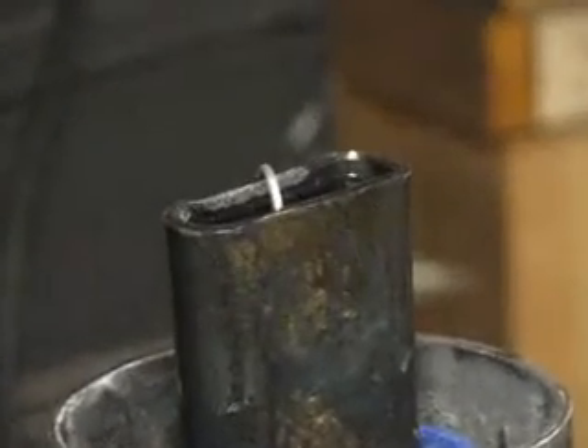Immediately after quenching, the blade is inserted in the tempering rig. After a few minutes, the temperature of the tempering rig is raised to 400 degrees Fahrenheit, and the sword is left for 1 hour.